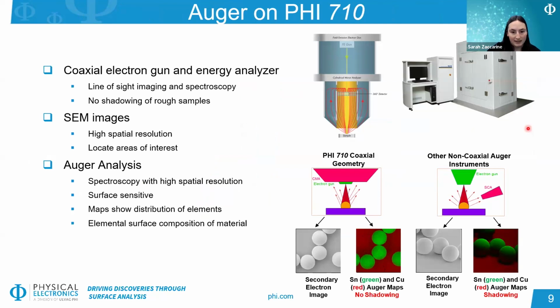On our PHI 710 system, this is a schematic of our electron gun and energy analyzer, which is coaxial. So this means that we have line of sight onto your sample. Our electron gun is coming directly from the top, normal to the sample, and then our analyzer is also normal to the sample. And this also gives us the ability to analyze rough samples because we will have much less shadowing. So this is very suitable for something like a nanowire or a particle.